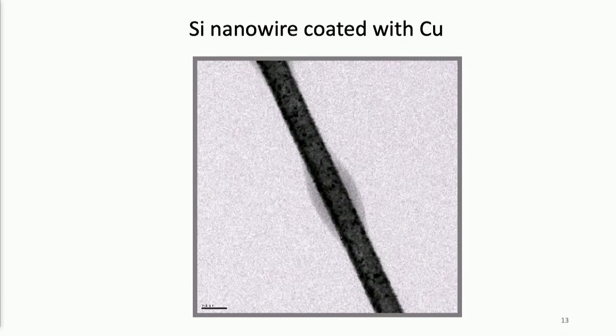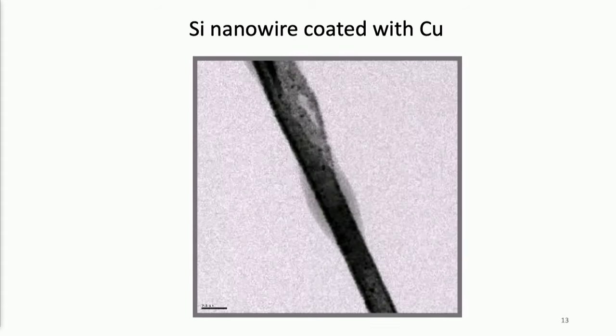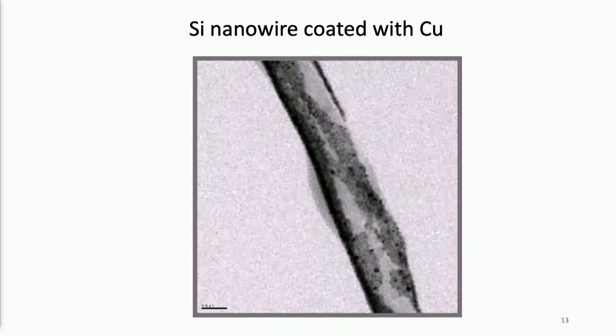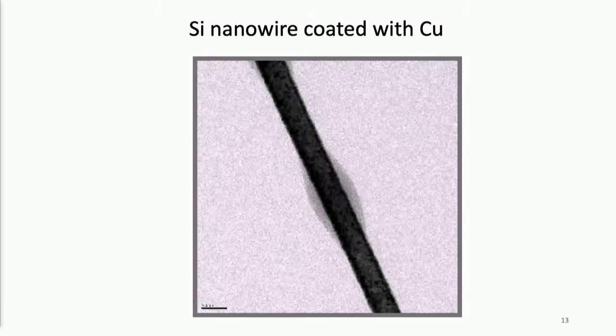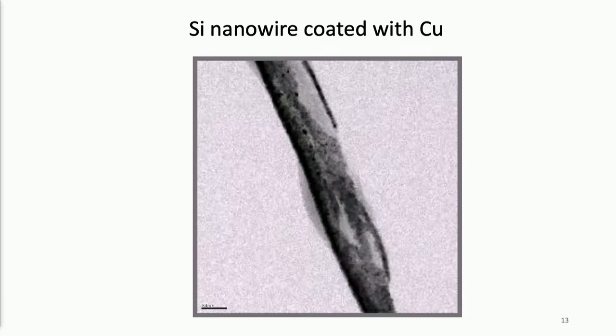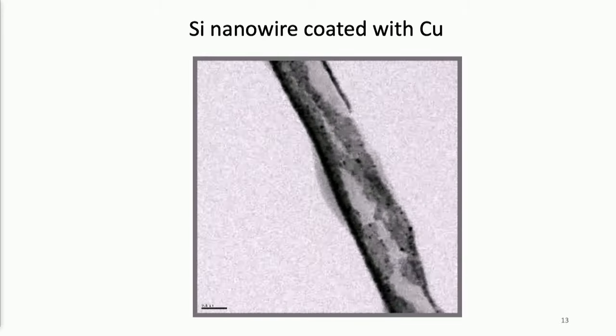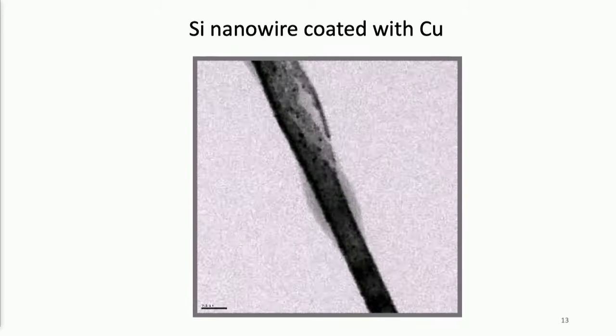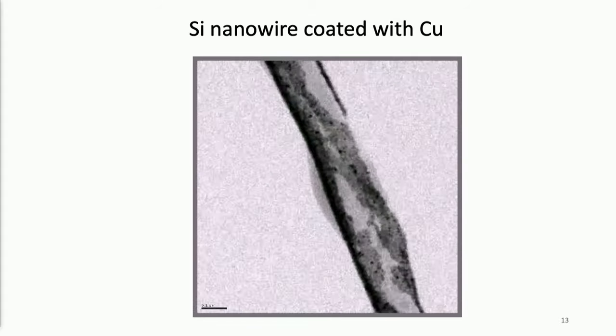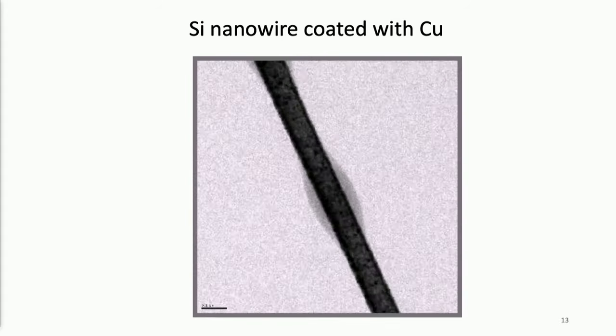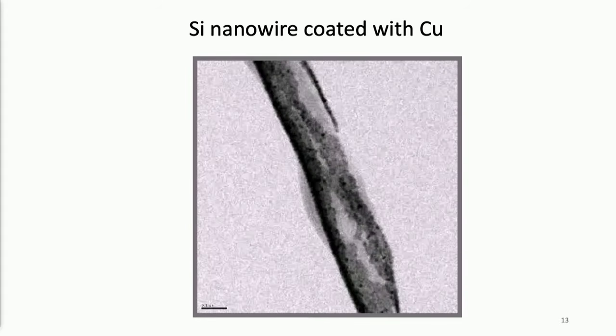And I want to show you a video. This is a 200 nanometer scale bar right here. So this nanowire diameter is about 1,000 times smaller than your hair in diameter. So if you charge it up, you see this nanowire expand a lot. With this black color coating, that's copper, it's broken. This expansion is so powerful, it actually breaks this coating. But when the diameter of the wire is small enough, they do not break anymore.